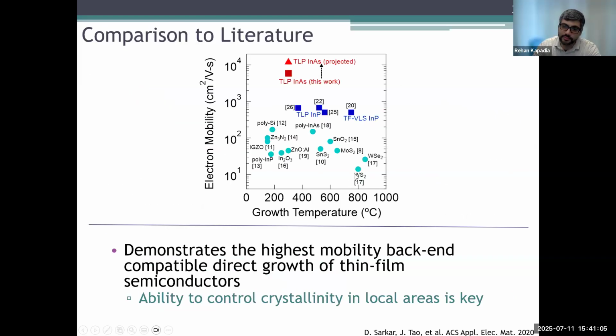And the key thing to put it into perspective is, if you look at what we showed over there, both through our indium phosphide work as well as our indium arsenide work, on a log scale, if you look at the quality of the material using electron mobility as a proxy, as compared to basically any other approach that you can find in the literature, you can see that it's essentially a line.